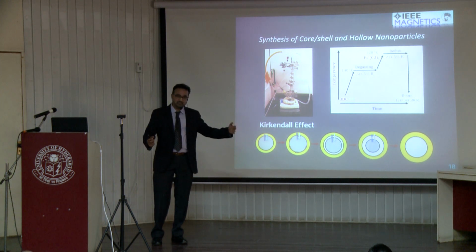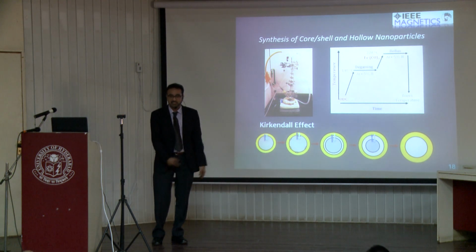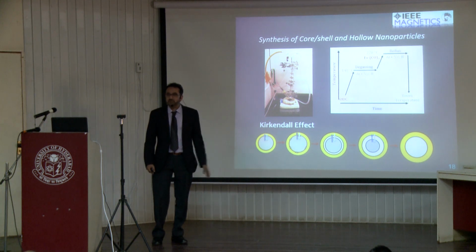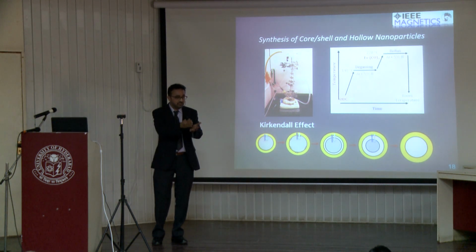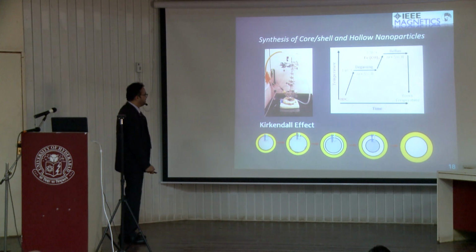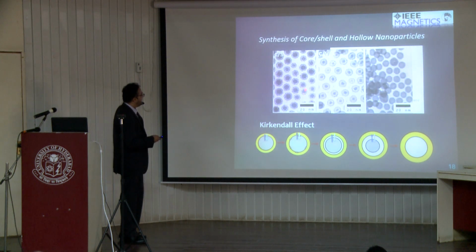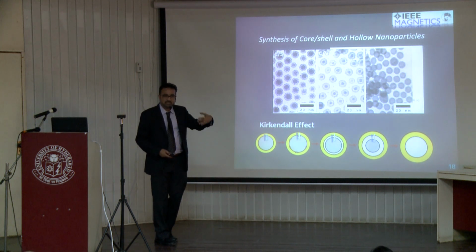In fact, Paul Alivisatos in Berkeley was the one who showed this first, that you can make hollow nanoparticles by this technique using the Kirkendall effect. However, it's not going to work for hyperthermia because your SAR is going to keep changing as the system changes. And in fact, for hollow nanoparticles, the SAR drops. Okay? So we measured this. In fact, we measured the magnetization of the core shell particles, then the core getting smaller, then hollow particles. We followed the whole thing structurally as well as magnetic properties, how they evolve.